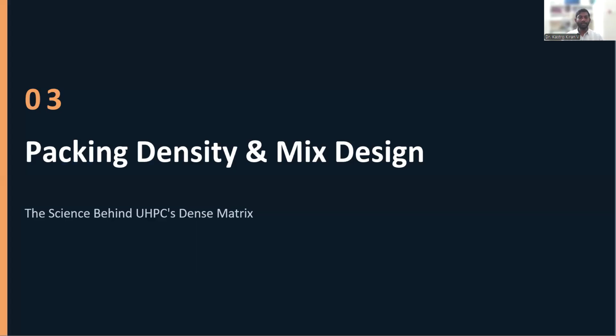And packing density is one of the most important things in the mix design of UHPC. Without doing a proper packing density analysis or packing density test, it is impossible to attain maximum packing. And if you are not able to achieve the maximum packing, obviously that leads to reduction of strength and a higher amount of pores, which will also cause durability issues as well.